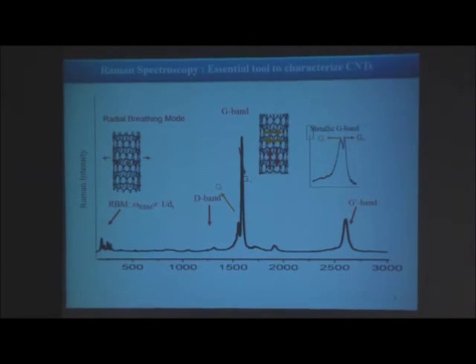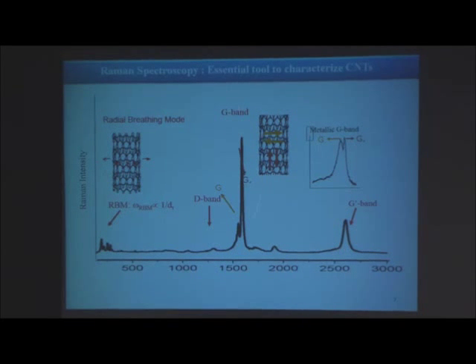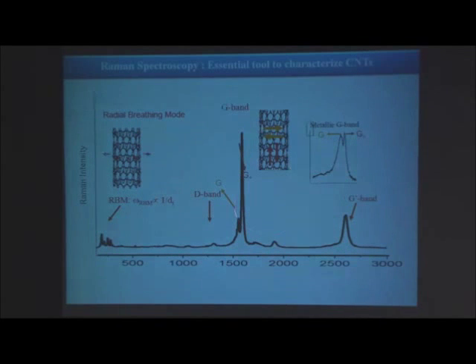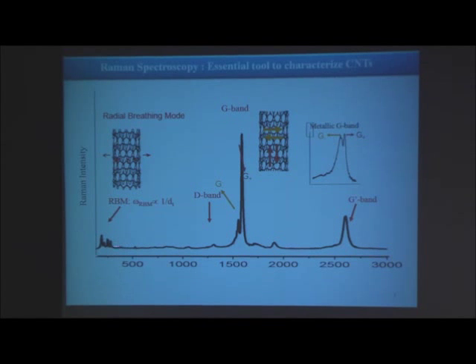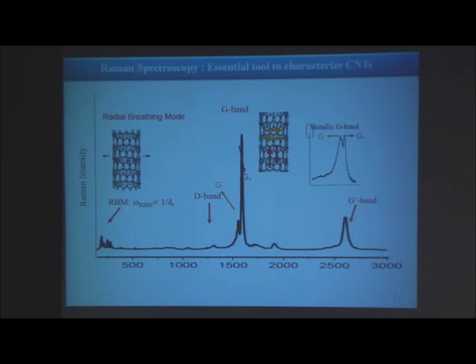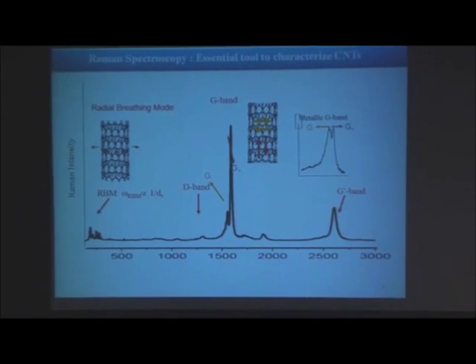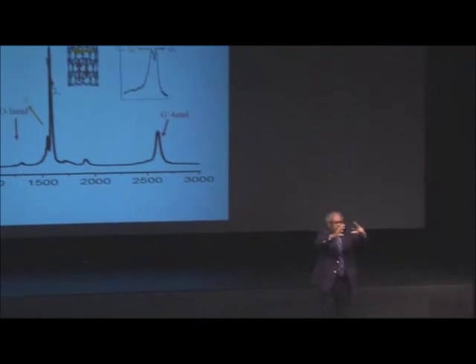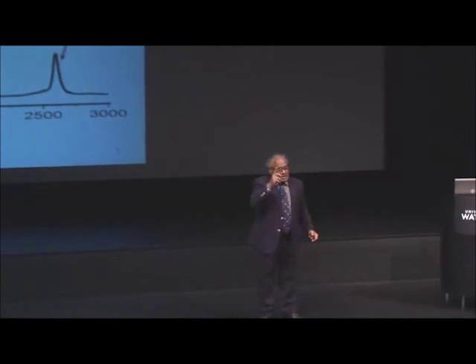That is nothing but a tangential mode, which is the G band in all sp2 carbon and also in the nanotube. What is more important is the small bands here at low frequency. These are the so-called radial breathing modes. You have a nanotube which breathes. When the nanotube breathes, that frequency of the breathing mode is inversely related to the diameter of the tube. So that is a very important thing, again, characteristic of the nanotube.